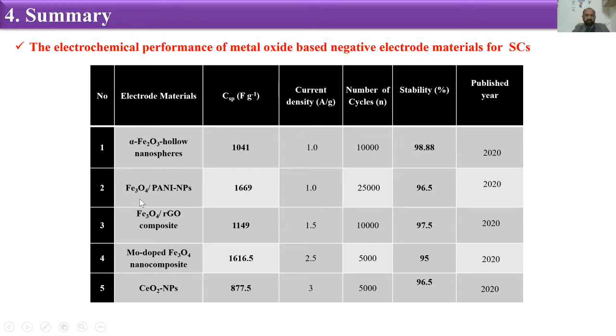We have published this article. For Fe3O4 nanoparticles, we have got this specific capacitance with this number of cycles and this stability retention, and again we have published this one. For the Fe3O4 MoO3 composite, we have this specific capacitance and the stability and retention. Similarly for the other composite, we have the specific capacitance and stability retention. And for cerium nanoparticles, we have got this specific capacitance with a stability of about 96 point something.